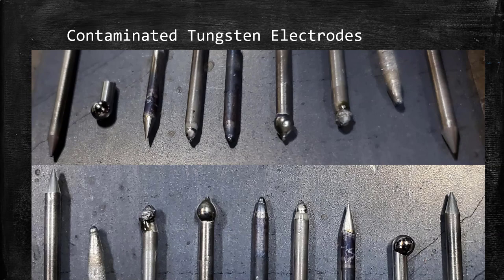Again, contact with the weld, contact with filler rod, using the wrong polarity, using the wrong filler rod, using the wrong shielding gas, not having enough shielding gas, too high amperage, so on and so forth. Lots of different things. And the form that your tungsten will take is not limited to the examples you see here. Honestly, there are probably a million different shapes and appearances that your tungsten electrode can take on once it's contaminated. So again, for comparison, if it doesn't look like the electrodes on the left or the electrodes on the right, then consider it unusable.